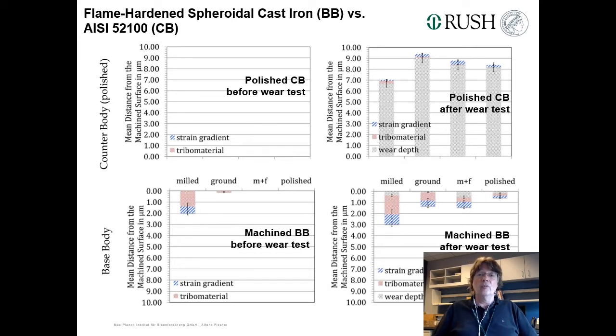on the good performance of the base body? I think it's not the magnitude of compressive residual stresses. It comes from the fact that it shifts the multiaxiality factor into the negative, meaning that crack initiation and propagation are hindered. If it would be on the positive side, crack initiation and propagation would be much more likely, excuse me, so that these 10% of stresses just bring about a very, very positive effect, and so the 52100 has no chance because it has no compressive residual stresses.